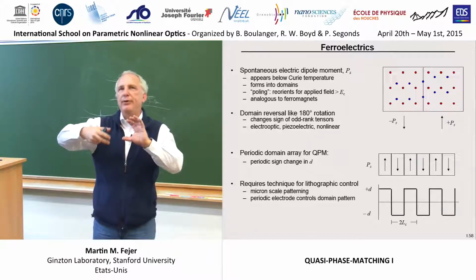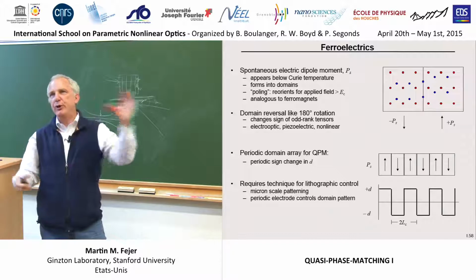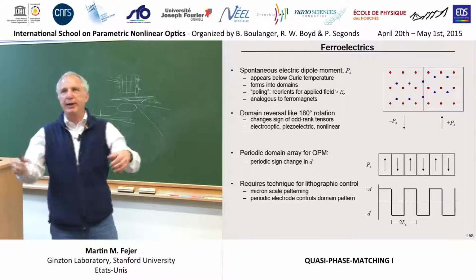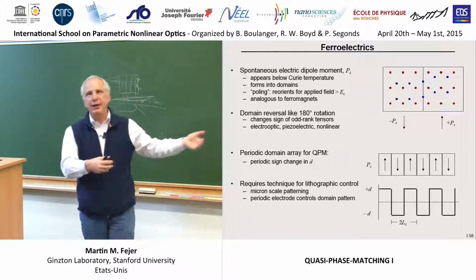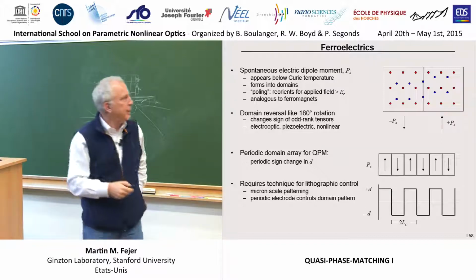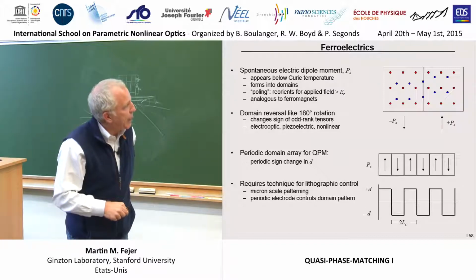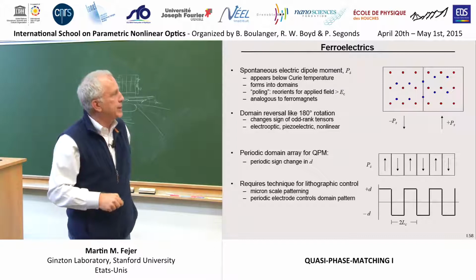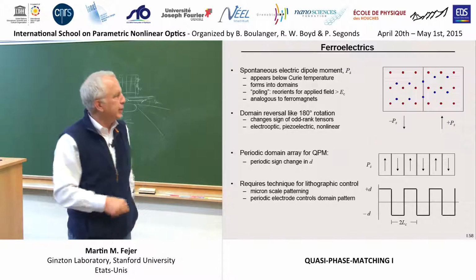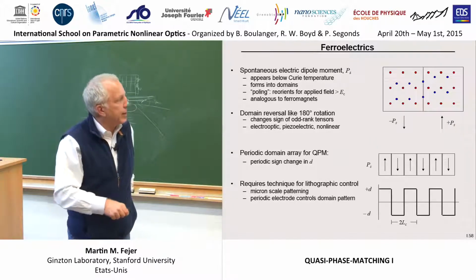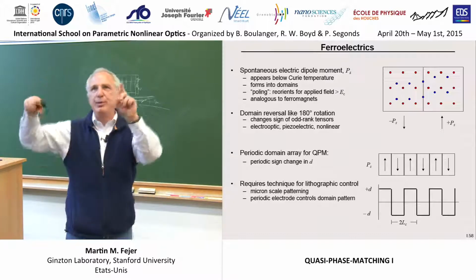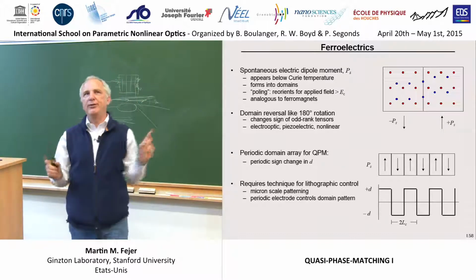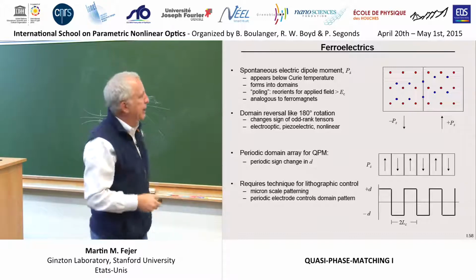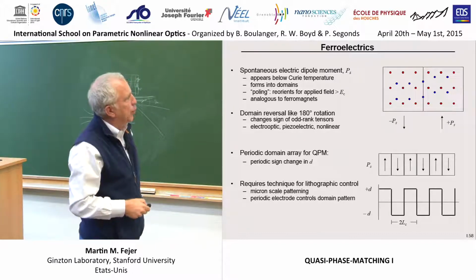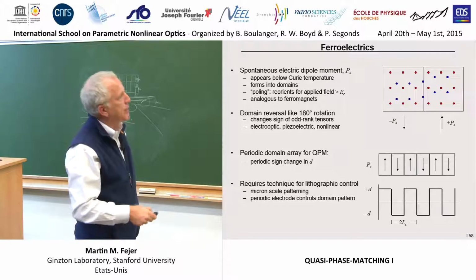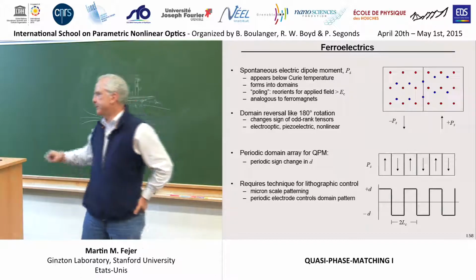And so this will flip the sign of such a 180-degree domain wall. You've changed the sign of all the odd-rank material tensors when you go from one side of the domain to the other. Piezoelectric, electro-optic, nonlinear optic, all of these tensors flip. And so if you can make an array of up and down spontaneous dipole domains in the ferroelectric, you are making the desired up and down sign of the nonlinear susceptibility that you need for quasi-phase matching. So what you need to do is figure out a way to, under good control, introduce such an array of domains.